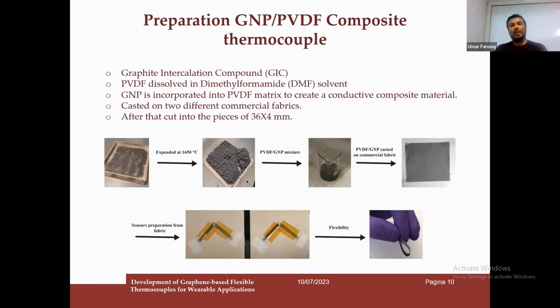So here is the method of how we prepared this type of thermocouple. First of all, we took commercially available graphite intercalation compound, and after that we took the PVDF and dissolved it in an appropriate solvent; you can use any appropriate solvent to dissolve it. The GNP and PVDF mixture was then deposited on commercial fabric and cast on different types of fabrics. After that, we cut these fabrics into 36 by 4 mm pieces and joined them together using silver epoxy.